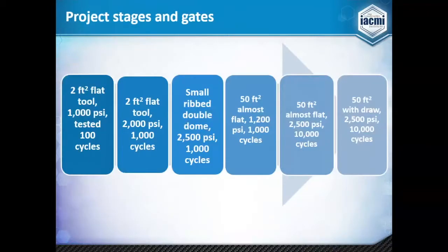So as we think about this, and we're still working through the timing on how long it takes to get there, but we see it as a progressive effort. Starting with something that's a relatively flat tool, to compression molding at 1,000 psi and achieving at least 100 cycles, followed by higher pressure and higher cycles. So we may be able to get through these first couple fairly quick, and then to look